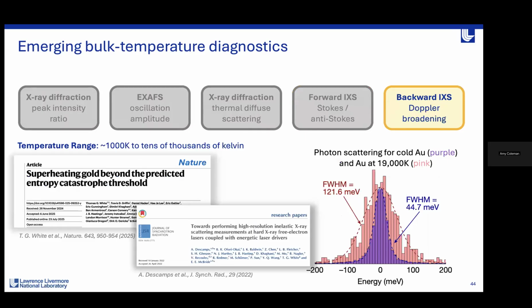The final technique I'm showing here very quickly is backward meV IXS. This is measuring temperature from thermal broadening of the elastic or Rayleigh peak at high momentum transfer. Thermal motion is what's causing the Doppler broadening of these scattered photons. By fitting this peak, you can infer the temperature.